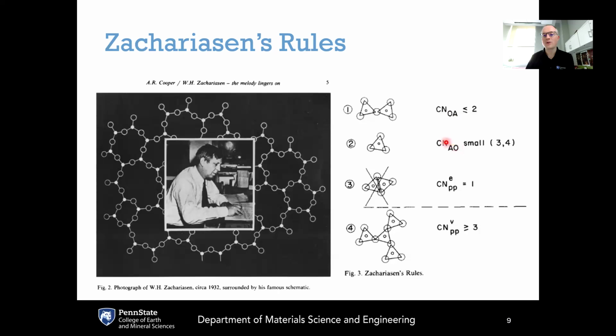Next is the coordination number of the oxygens around the cation. Notice that the subscripts here are switched. This means that the coordination of the oxygens around the cation is small, specifically 3 or 4. And here you can see the cation in the center of the polyhedron, coordinated with 3 oxygens. So we've got 3 oxygens around the cation, and this forms our basic structural unit, the triangle. If you were to have 4 instead of 3, there would be another oxygen coming out of the plane, and this would be a tetrahedron instead of a triangle.